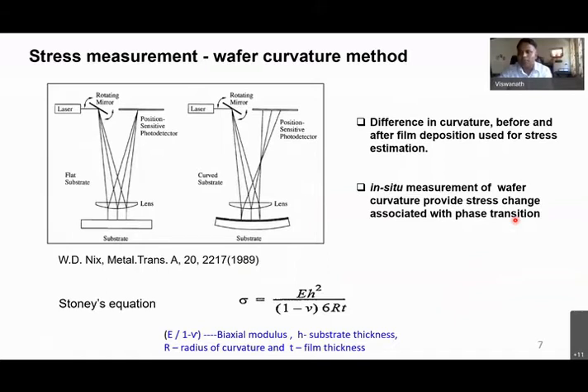Let me just give you a probably basic introduction about how we actually visualize or measure the stress or the actuation. For thin films, it is well established, right? The famous Stoney's equation. This is again a Nix paper in 1989. We all know that thin films are always under stress, right? Freestanding is free from stress. The moment you try to deposit or attach your thin film to the substrate, they are no longer free, either to expand or contract.